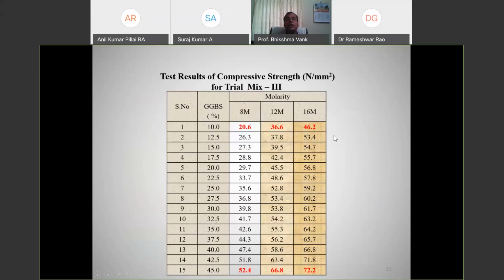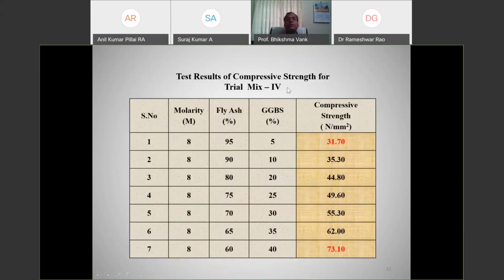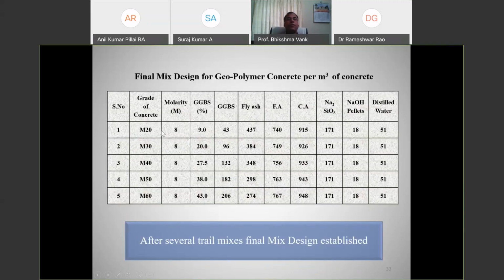And then trial mix 3, we got like this: 8 molarity, 12 molarity, 16 molarity, 46 to 72. The results of compressive strength for trial mix 4, 31 to 73. This is the final mix we got. What we have done is, at our university, we have taken only 8 molarity. For 8 molarity, we have concentrated more on compressive strength for 20, 30, 40, 50.